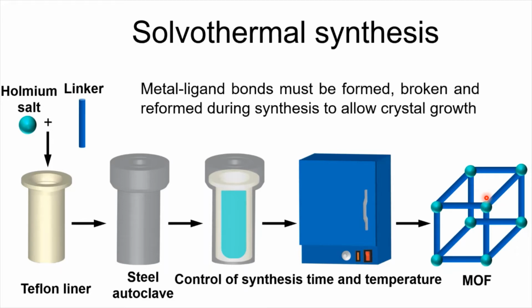Of course, you can modify the pH, the initial pH of your solution. You can modify the concentration of your precursors. You can change time, you can change temperature. All these variables, while they seem minor, they really impact the final structure.